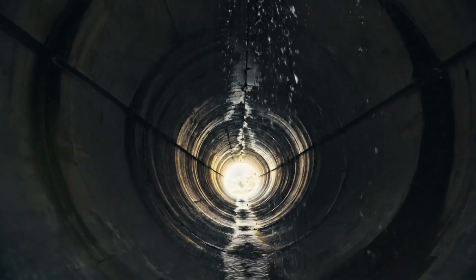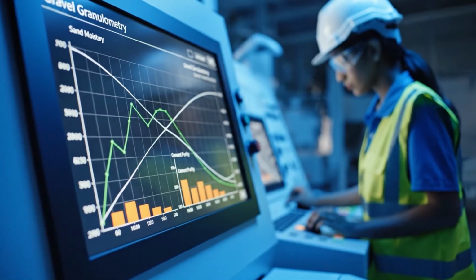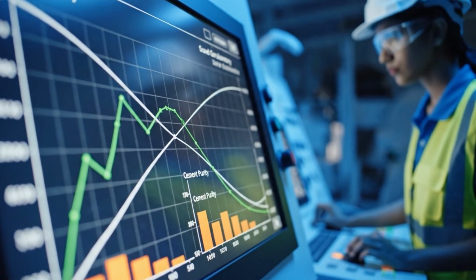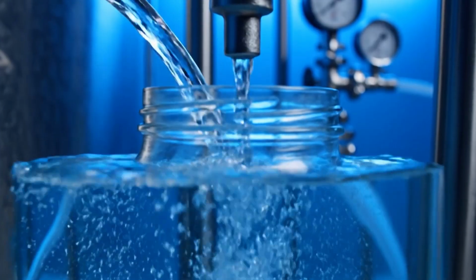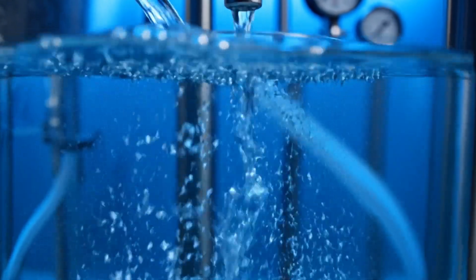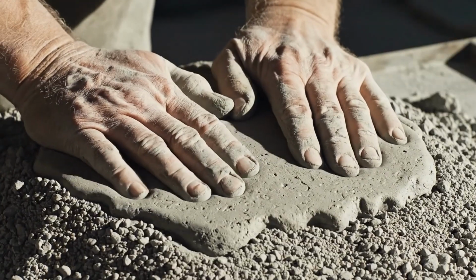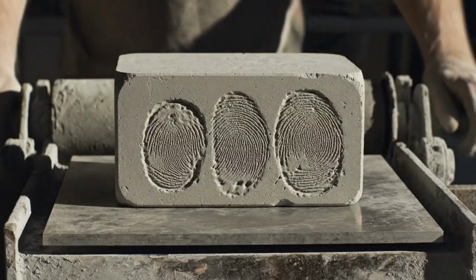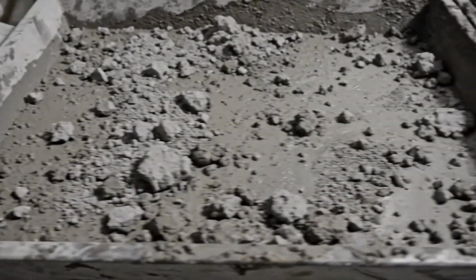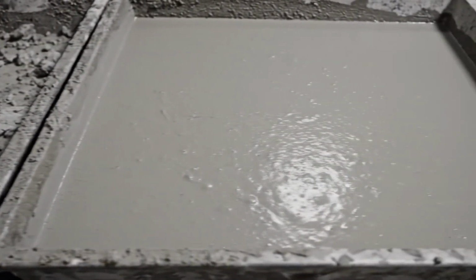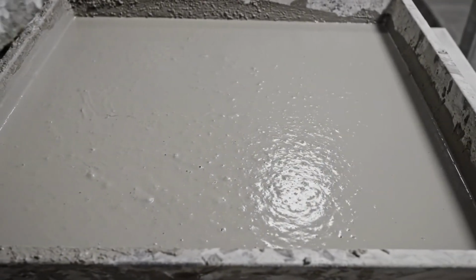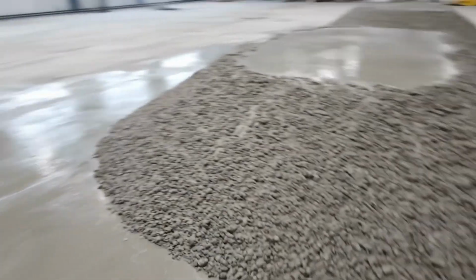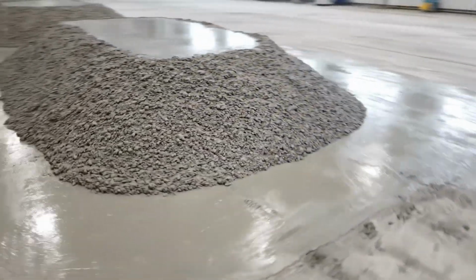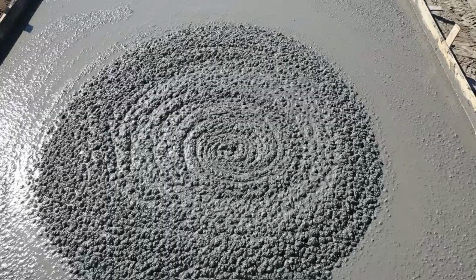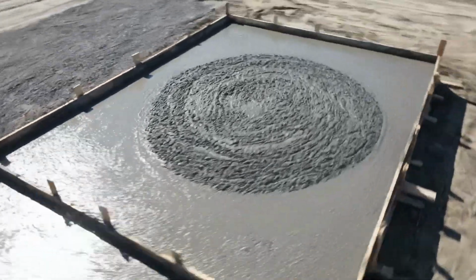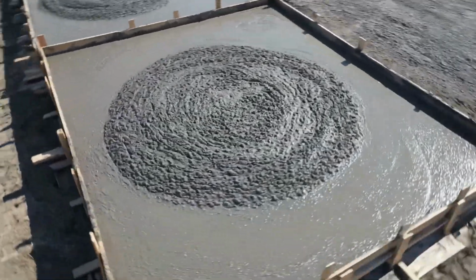In a buried pipe, any error of origin can be amplified over the years until it becomes cracks, leaks, or structural failures. Water, although it usually seems like the simplest component, is also rigorously controlled. It must not only be clean, but also exactly dosed. In the production of concrete pipes, the mix cannot be as fluid as the conventional concrete used in columns or slabs. Here, a much drier consistency is sought with low workability, capable of maintaining shape and compacting efficiently through vibration, compression, or rotation. If too much water enters, the mix loses density. If too little enters, hydration may be incomplete and the internal structure does not develop its full strength.